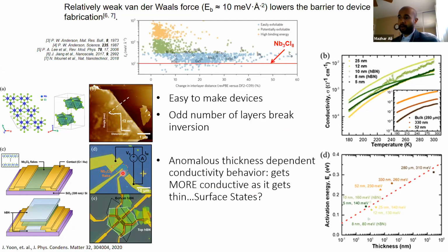Now, in terms of our general bulk exploration, we found something very surprising in that as you made this thing, oh, it's kind of low resolution. Well, it's hard to read here, but basically as you go thinner, the conductivity increases, which is not normal. That is unusual. It's sometimes been seen in things that have, for example, surface states. But it's also sometimes seen in things that have multiple conductive channels for various reasons. But we wrote this paper where we found that this behavior was intrinsic.